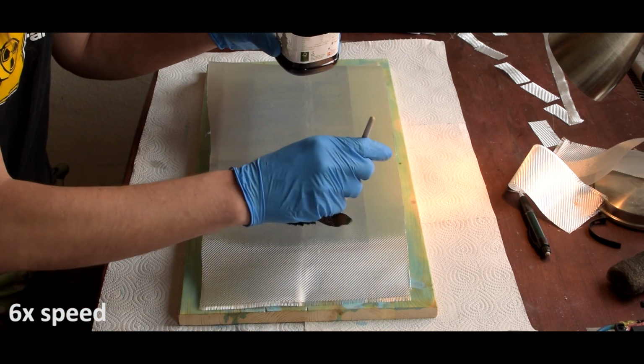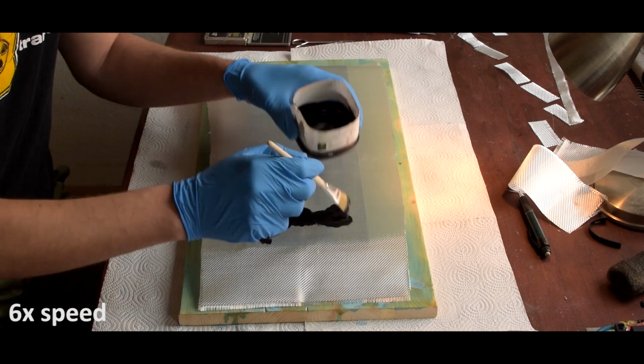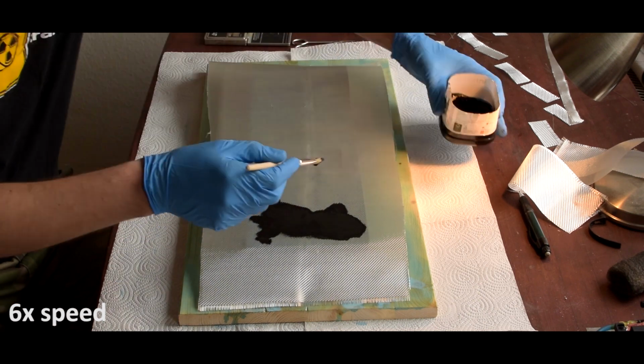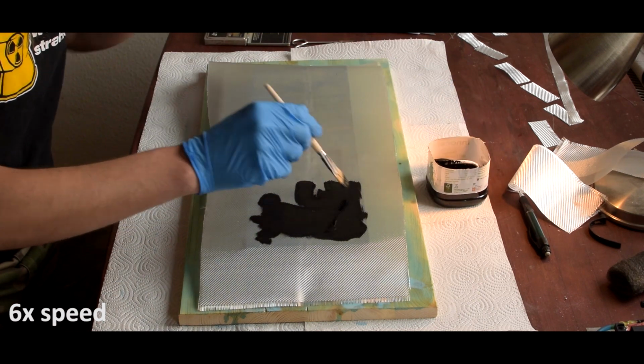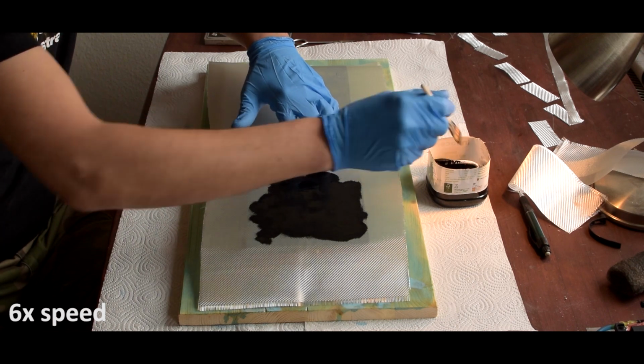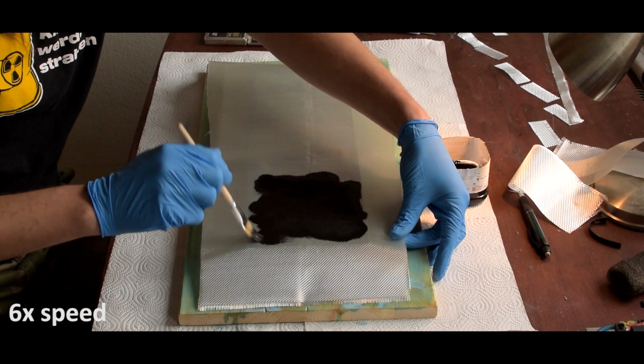When applying the resin, spread it out from the middle. Try to avoid wrinkles and air bubbles beneath the tissue. Don't add too much resin, you don't want puddles of it, just enough to soak the tissue.